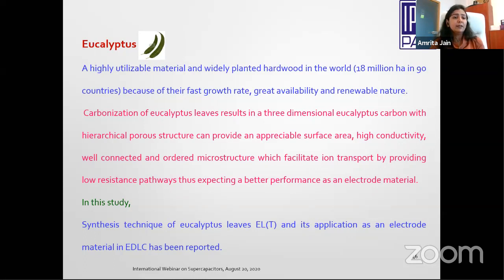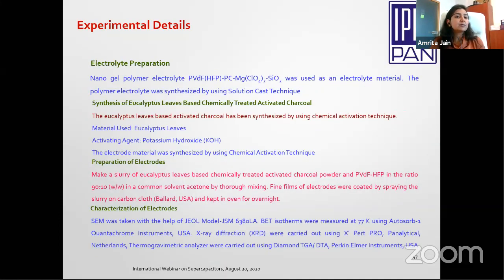So in this study, we have synthesized carbon materials from eucalyptus as an electrode material for EDLC applications. For the electrolyte, we have synthesized a nanogel polymer electrolyte using PVDF-HFP. PVDF-HFP is one of the very common polymers used, polyvinylidene difluoride hexafluoropropylene, with PC, propylene carbonate, and Mg(ClO4)2, which is magnesium perchlorate.